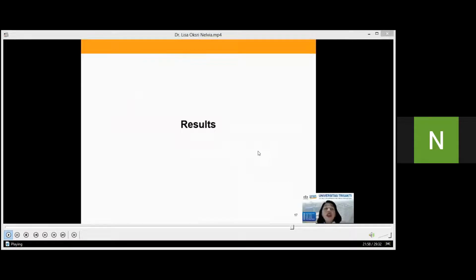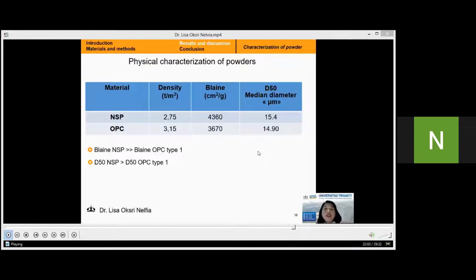I move on to the third part of this presentation, which will be some results of the study. The results obtained from the absolute dry density, specific area, and the median diameter are shown here. The absolute dry density of nickel slag powder was 2.75 tons per meter cube, and the cement was 3.15 tons per meter cube.